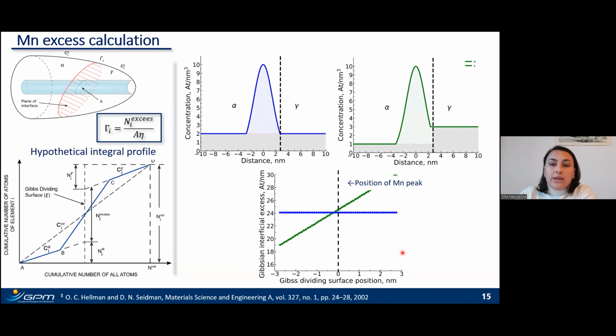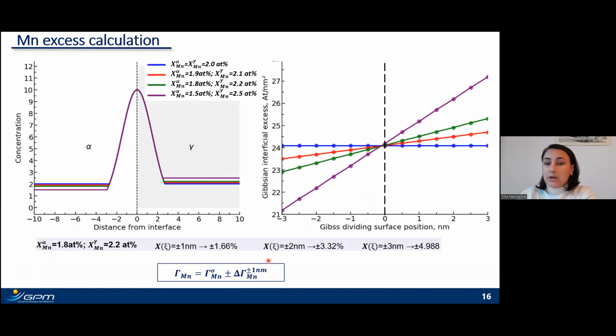Logically, we can place it at the peak of the composition profile, but there is no strong argument that this is the correct choice. And for the moment, there is no unique solution in the literature on how to define the position of the dividing surface in the case of a heterogeneous system. So we decided to estimate how the manganese excess value is affected by mispositioning of the dividing surface within the manganese peak, within a few nanometers, because that is approximately the manganese peak width observed experimentally.